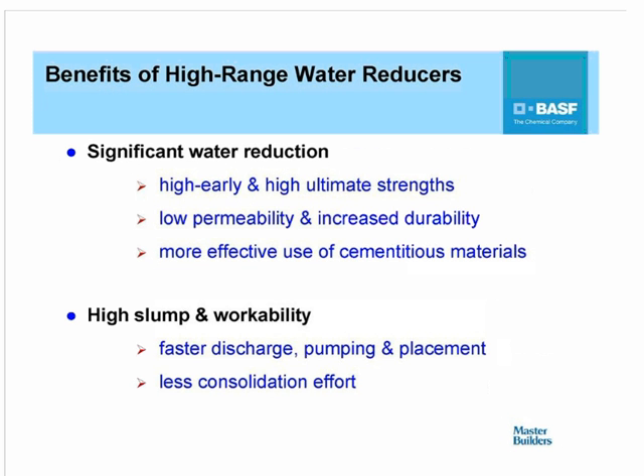The main benefits of high-range water-reducing admixtures lie in the fact that they do provide significant water reductions, as we saw on the previous slide, anywhere from about 12 to 40%. And as a result of that, they are the main admixture of choice in producing high early strength as well as concrete that have high ultimate compressive strength. They are also the admixtures of choice when we're looking at producing concrete with low permeability or increasing the durability of concrete. And they also provide more effective use of cementitious materials in concrete.